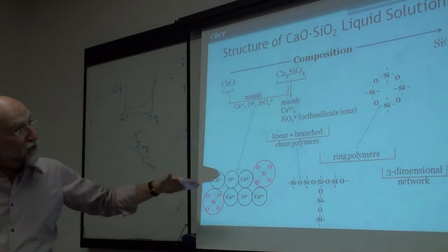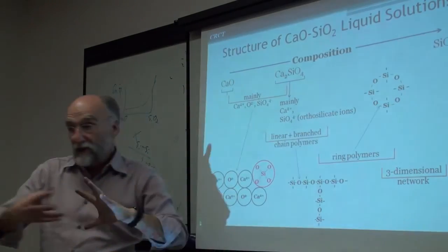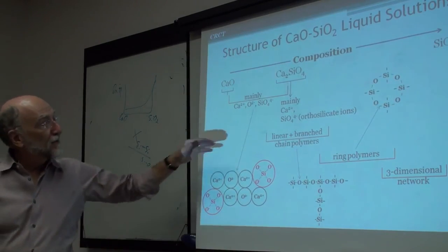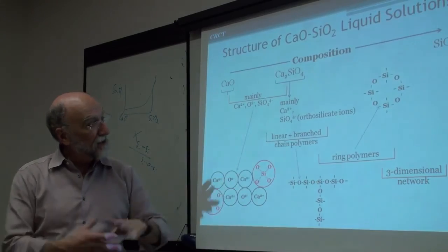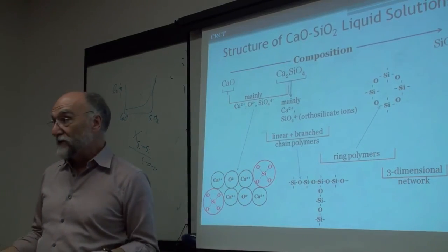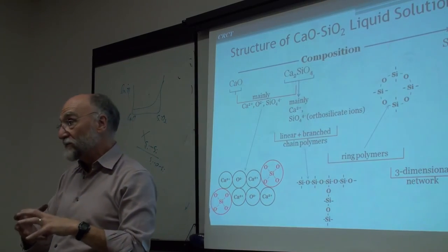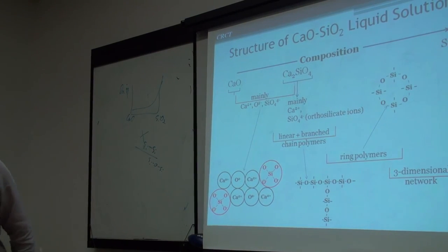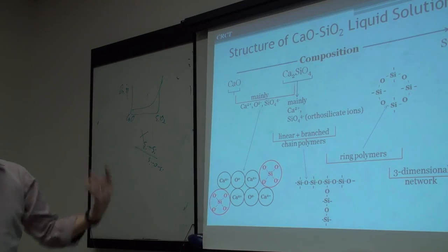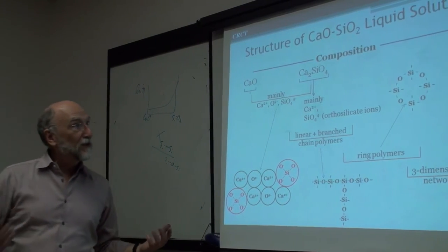The viscosity only goes up when you start to have a large interconnected system. Just having a few dimers and trimers doesn't do an awful lot for increasing the viscosity. It only goes up when you have large clumps. It will depend on clumps of 15, 16, 17, 18.